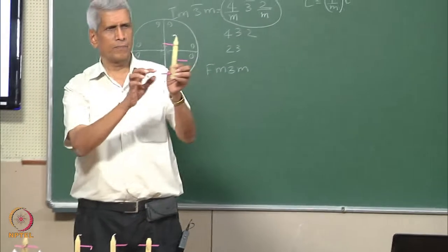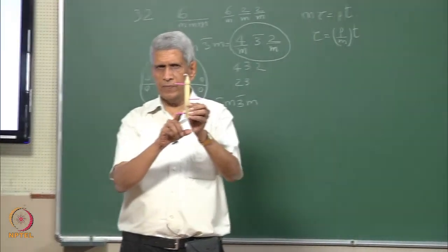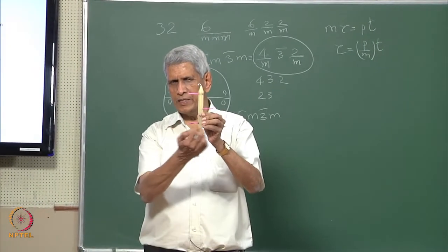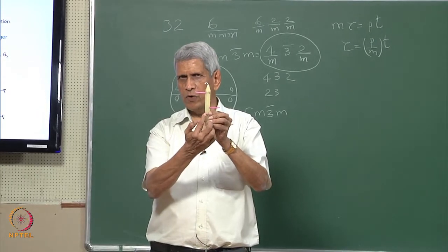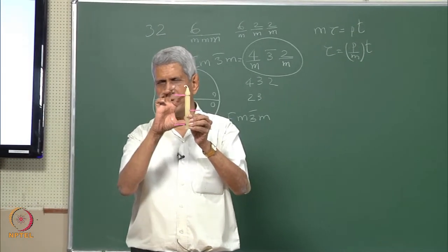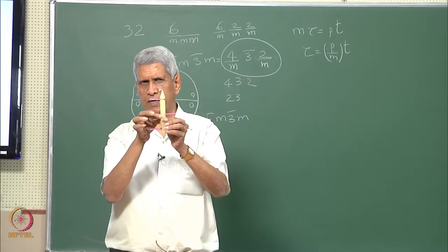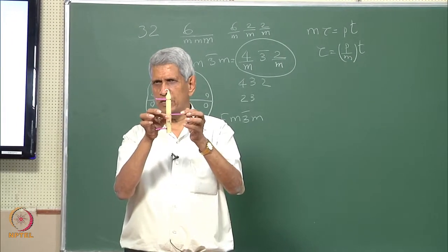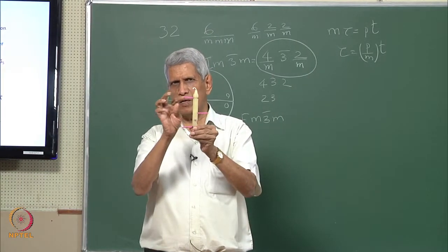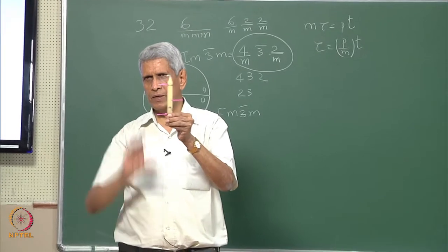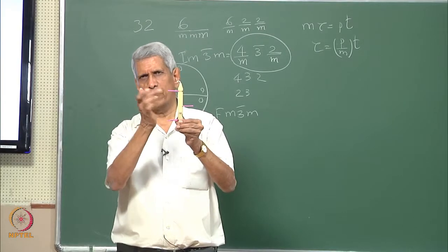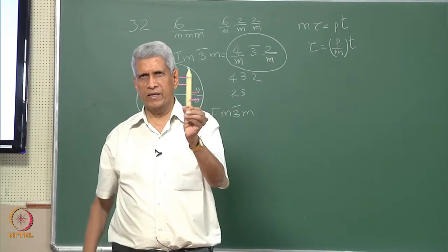You look at this here. From here, there is a motif which is being kept here. It has been rotated by 90 degrees and shifted by 1/4 of the lattice parameter in that direction, that is, the translation vector in that direction. It reaches here. Again rotated, it reaches at the half. Again rotated, it comes here. The fourth one, it has come back to an identical position, correct? From here 1, 2, 3, 4. One is here. Okay. So this has come back.